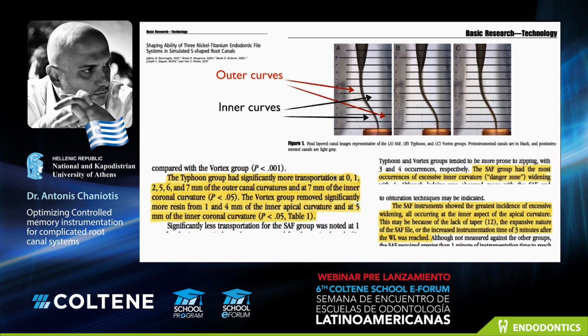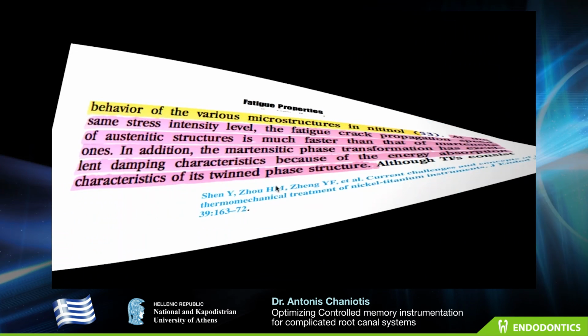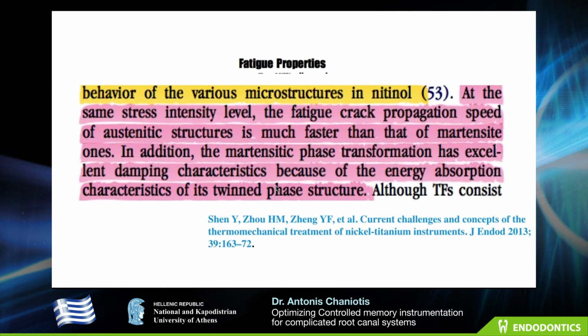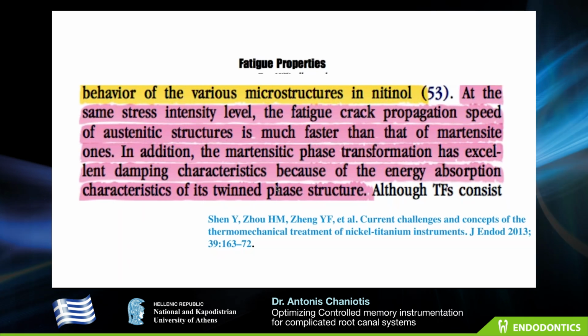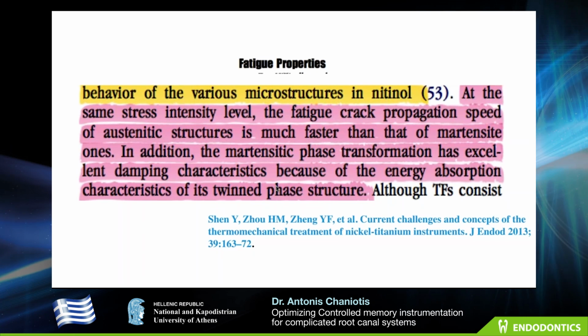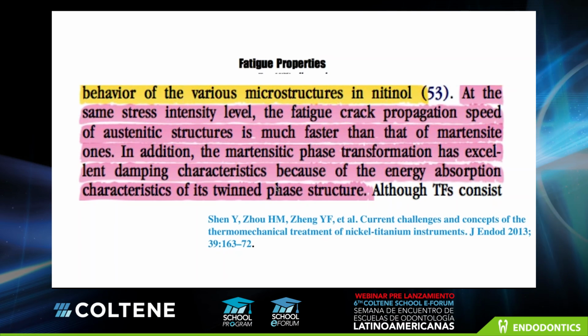Moreover, a hybrid microstructure with a certain proportion of martensite, like the HyFlex, is more likely to have more favorable fatigue resistance than a fully austenitic microstructure because of its dampening characteristics. Because at the same stress intensity level, the fatigue crack propagation speed of austenitic structure is much faster than that of martensitic ones. How much faster?